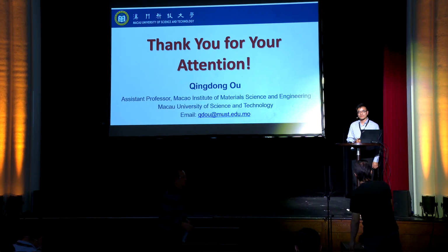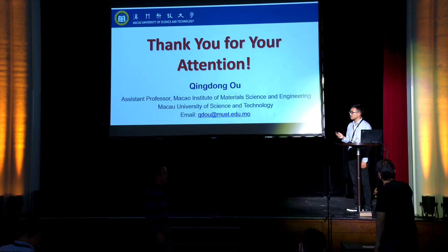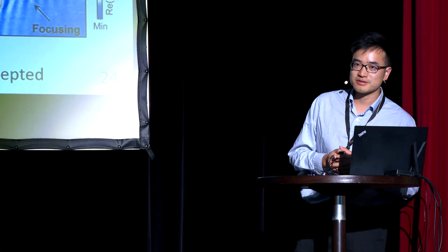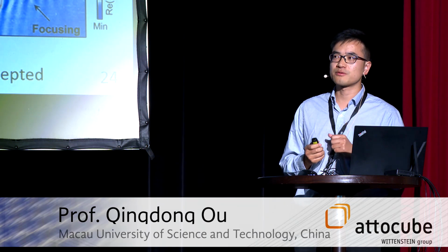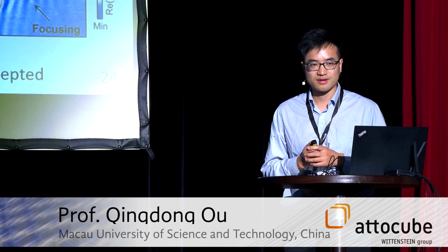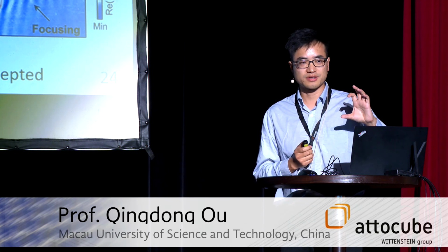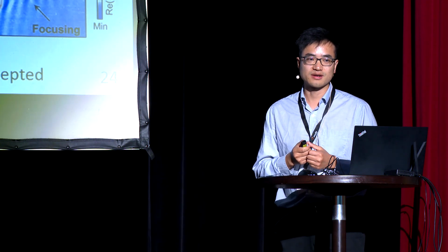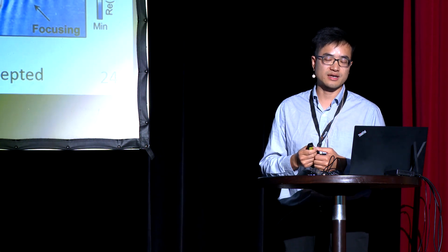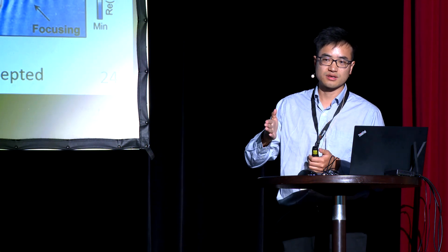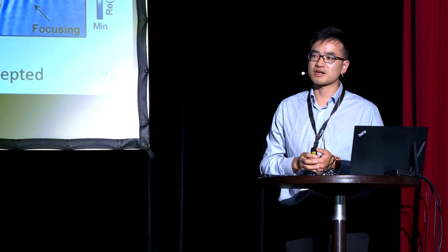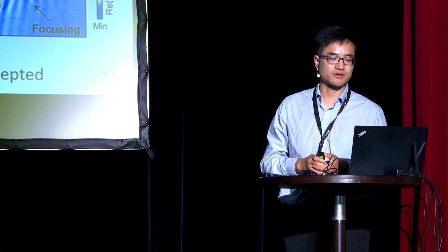Very nice talk. What's the depth you can probe with the last thing you demonstrated? Is it through MoO3, and what's the thickness? In the theoretical calculations, we're using 500 nanometers, but in the experiment, we are using 250 nanometers. I think it can be thicker but might compromise the resolution, because in the canalization region, theoretically the rays of phonon polaritons could be very straight. Yes, canalization is the main point of this kind of lens.